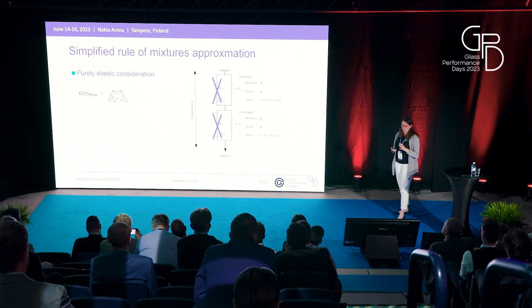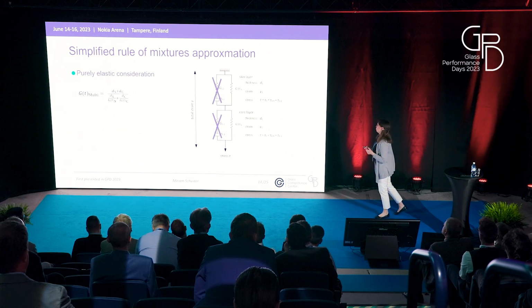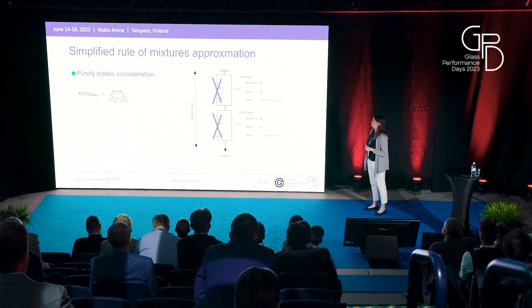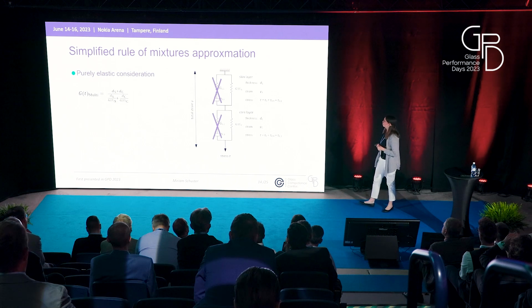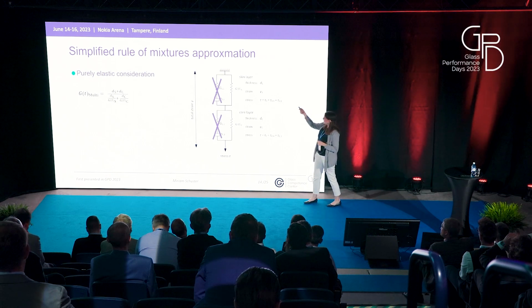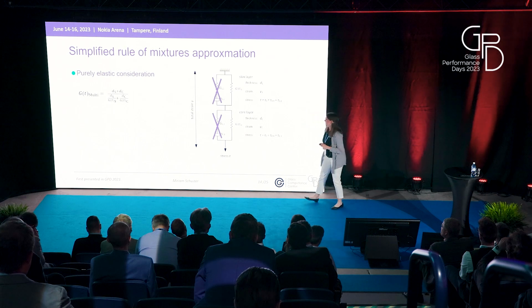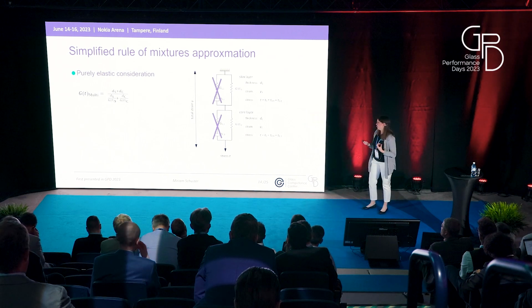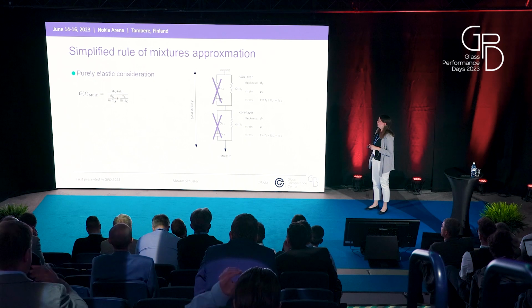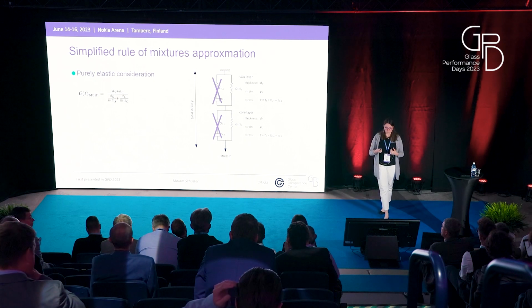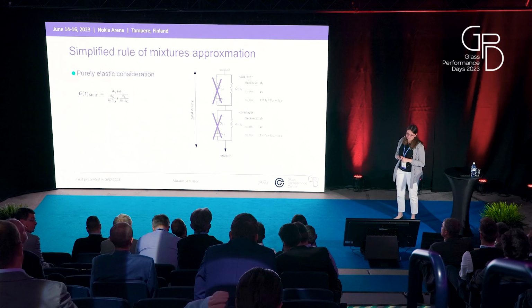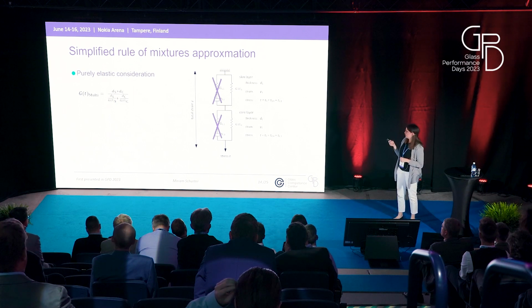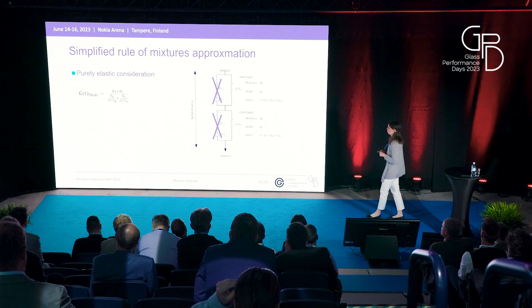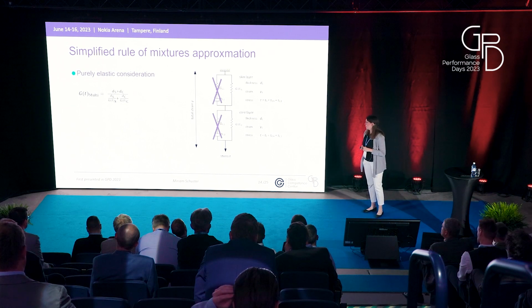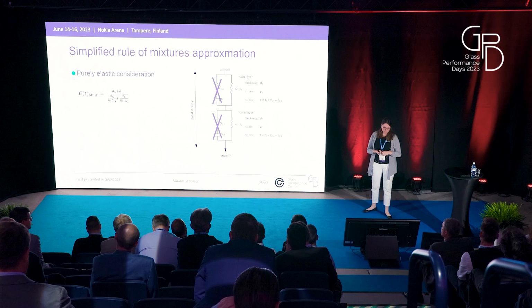However, besides those longer or more complicated combinations, we also considered a simplified rule of mixtures. In this model, the Maxwell elements of the individual layers were neglected, and only the elastic springs were considered. And the stiffness of those elastic springs is in fact dependent on time. And we see that here the solution is very short, and of course we obtain a very quick prediction of the material behavior of the multilayer.